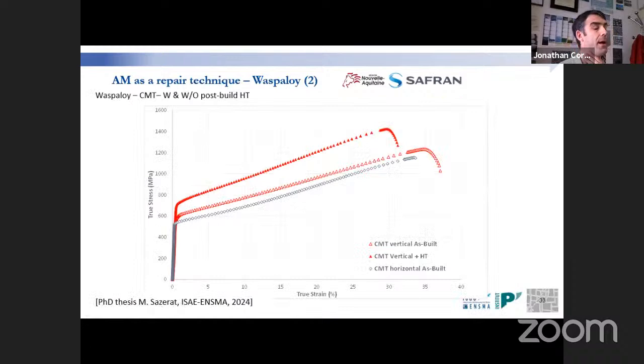I just want to show you here the case of CMT processed Waspaloy. That's a kind of wire arc additive manufacturing technique. So here you have the tensile properties at room temperature of CMT processed Waspaloy, vertical and horizontal directions, as built, and with a subsequent heat treatment. What we learned from that is that just after the CMT process, we are out of equilibrium. That's important when you think about the relaxation of residual stresses, because on the one hand, you introduce residual stresses due to the thermal field and the buildup of dislocation density within the material during processing.